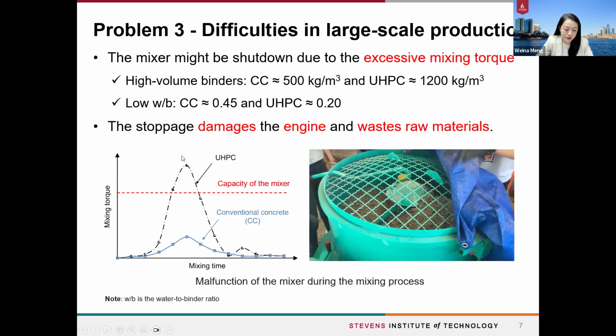The reason is that, as you can see in this figure, it shows the mixing torque evolutions for conventional concrete. The peak mixing torque is very low. It's much lower than the capacity of the mixer. So that's why for mixing conventional concrete, there's really not a problem.